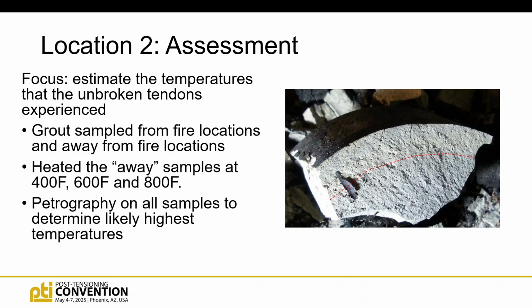And the petrographers are very good at determining the impact of the heat on concrete and how hot it got and how deep it was by looking at the aggregate colors in petrography. But grout's a little bit different because there's no aggregate in it. So what we did was we took some of our unaffected samples and we cooked them at various temperatures for an hour to try to develop that internal heat damage of the grout samples so that our petrographer could have a fingerprint to look for on our heat affected samples, right? Because we needed to know how hot those grout samples got. And we did petrography on all the samples.